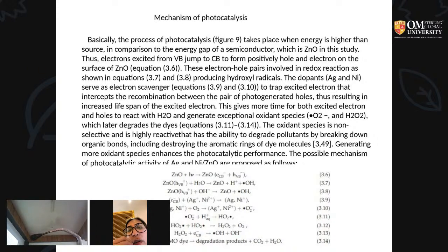The mechanism: zinc oxide, in the presence of sunlight, releases an electron to the conduction band. These electron-hole pairs are involved in a redox reaction, as shown in equations 3.7 and 3.8, producing hydroxyl radicals. The dopants, silver and nickel, serve as electron scavengers, equations 3.9 and 3.10, to trap the excited electrons. That intercepts the recombination between the pair and the photo-generated holes, thus increasing the lifespan of excited electrons. This gives more time for both excited electrons and holes to react with H2O and generate exceptional oxidant species,